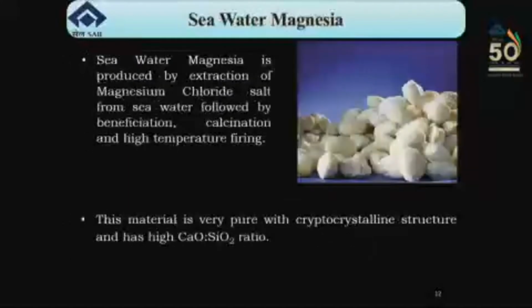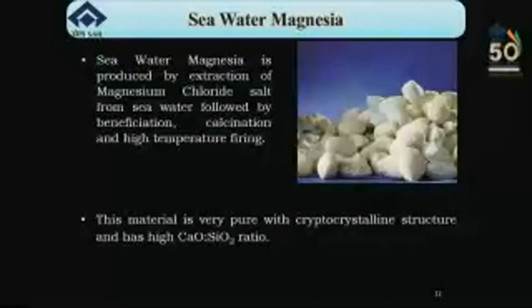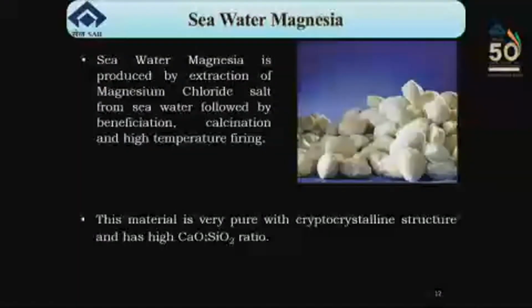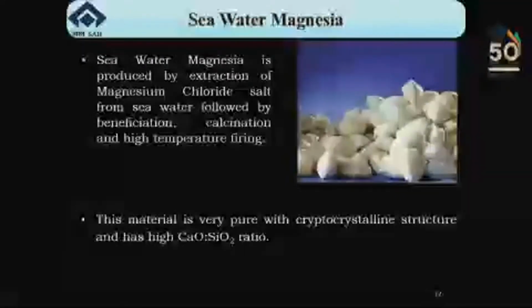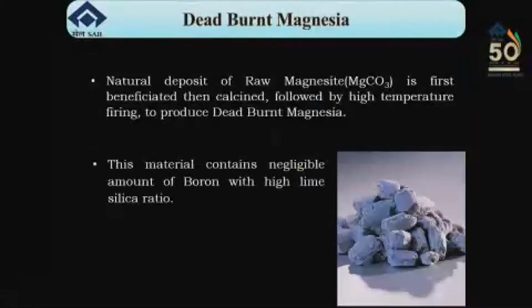Seawater magnesia, as the name suggests, is produced by the extraction of magnesium chloride salt from seawater, followed by beneficiation, calcination, and high temperature firing. This material is very pure with cryptocrystalline structure and has high lime to silica ratio.